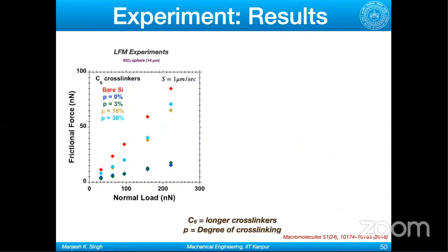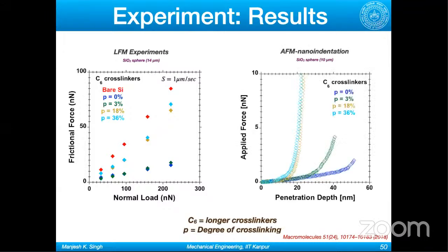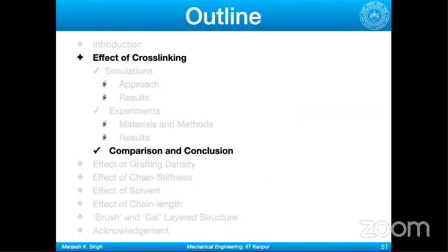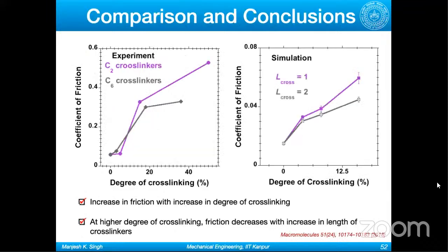Again, we repeated the same experiment for C6, the longer cross-linkers, and we have a similar trend here as well. I'll just quickly move to the coefficient of friction part. I have shown here only the simulation results. I've not told you the simulation details. What we can tell clearly from here is that as you increase the degree of cross-linker, your coefficient of friction goes up, both in simulation and experiments.